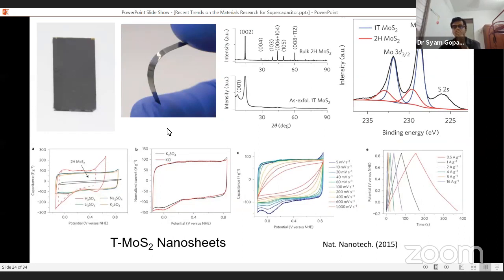Then one particularly interesting piece of research we have found is synthesizing metallic molybdenum disulfide nanosheets by selective etching. That means certain layers of this molybdenum disulfide are removed by the selective etching process. Here, testing this in potassium sulfate as well as KCl solution, the CV shape we are observing is almost symmetric. That means as it's symmetric, we can say that it is a pseudo-capacitor material compared to a battery material. Here not that many redox peaks are coming, even though Faradaic reactions are there.